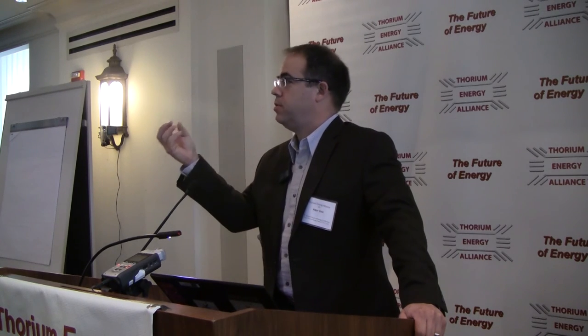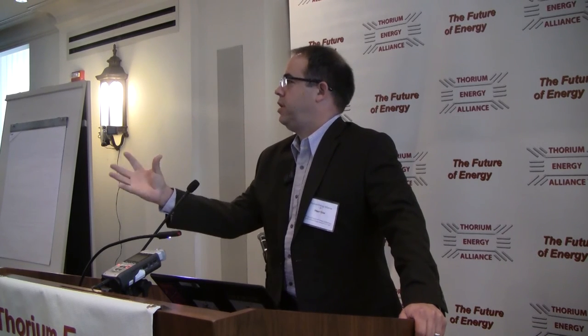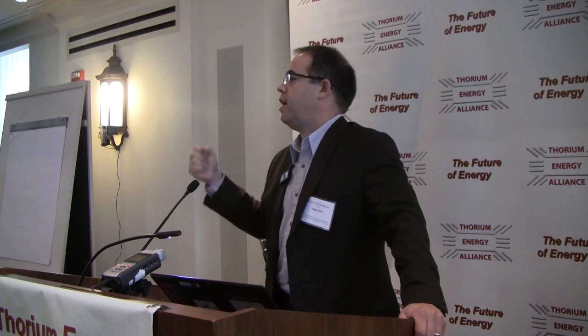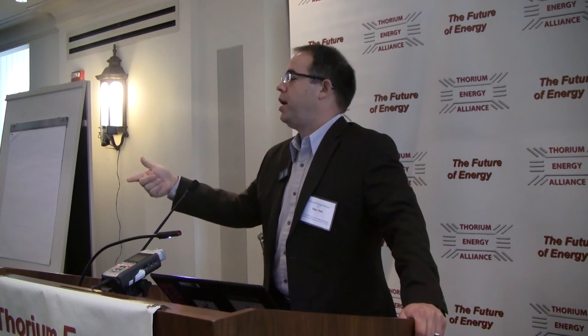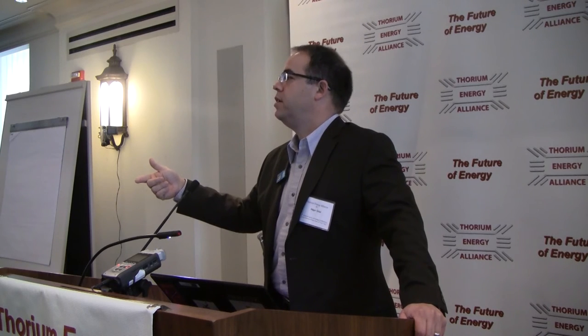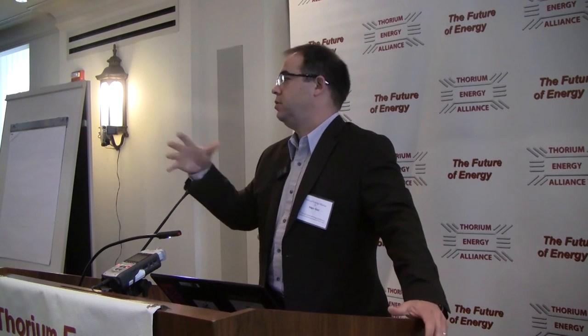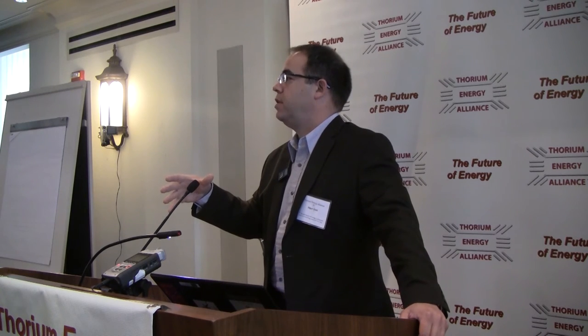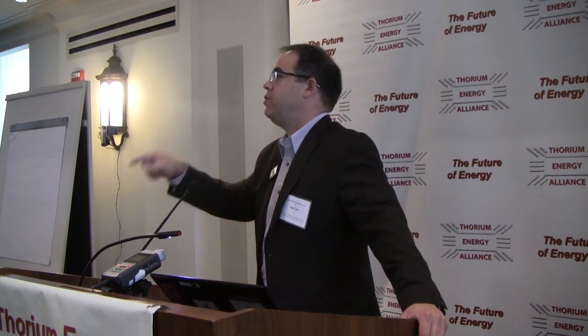In fact, I would take chunks of beryllium fluoride, put them on the table, and it would melt and look gooey. What it's doing is taking that moisture, making beryllium hydroxide plus hydrofluoric acid. But if you do it in an enclosed, neutral, controlled atmosphere, and you add the lithium fluoride or the other salt, then you've stabilized that. Right, and the equimolar sodium fluoride-beryllium difluoride is lower melting than Flibe, and we don't have to worry about pure lithium-7 for the first generation. Exactly. Yep. I think I'm running out of time right now.